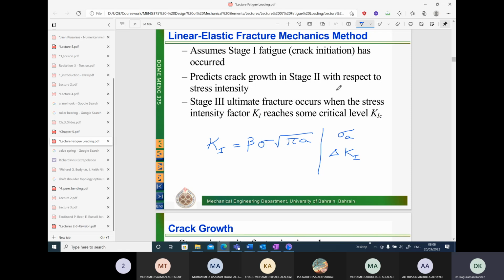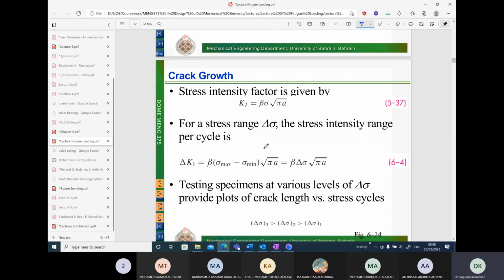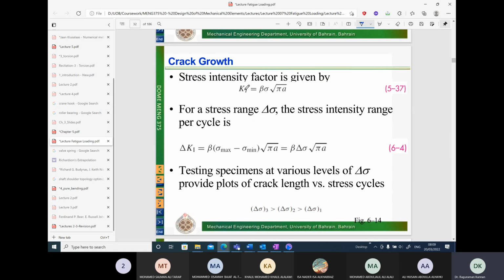So in stage 2, the life of the specimen is found out. As long as stage 2 persists, life is there, and when it reaches stage 3, we have the ultimate fracture, brittle fracture to be more accurate, and it is catastrophic fracture. When Ki reaches the KIC value, then brittle fracture takes place. In the same way, we have to get a relationship. So let's see the equations. So the stress intensity factor is defined in this way. Using the sigma max and the sigma minimum values, we obtain delta Ki, and we get that.